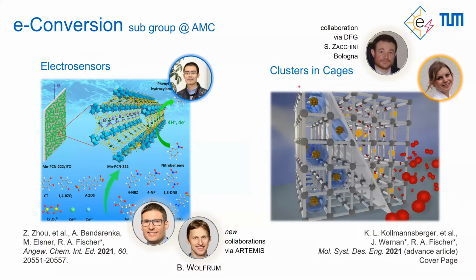Just mentioning another example, which we call clusters in cages. This is Katrin Kollmannsberger, and also Julian is involved in this. Here we integrate atom-precise clusters made by wet chemistry into the cages of a MOF to keep them, so to say, safe from aggregation and growth by the confinement, and to allow for the investigation of their catalytic properties in such a hybrid system. But now let's zoom into this project for a moment.